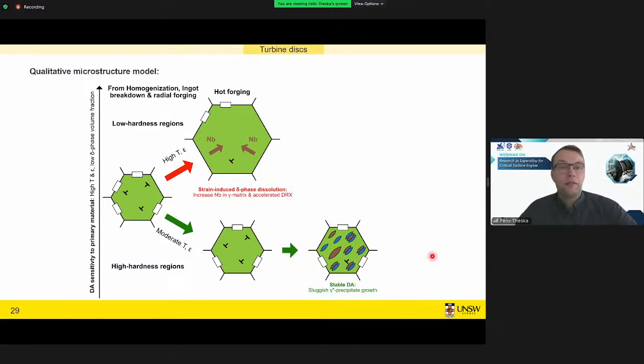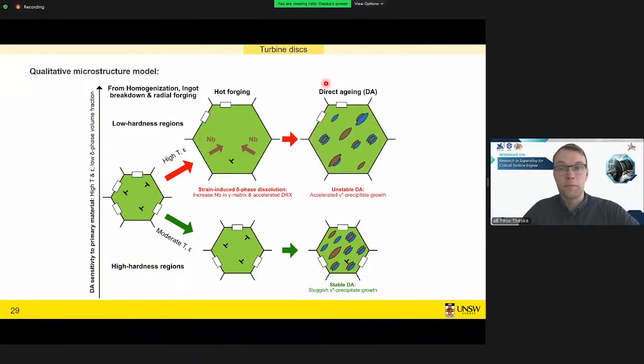Now our low hardness regions correlate with a high temperature and high strain. And what this can do is actually dissolve some of the delta phase, which would result in a lower volume fraction. But if the delta phase is dissolved, this means we have more niobium in solid solution and fewer dislocations as well. So we have this grain growth occurring, more niobium, fewer dislocations. And that's in favor of more widely spread precipitation. I call this unstable direct aging for the reason that there are fewer nucleation sites and the growth is very much accelerated due to more niobium.